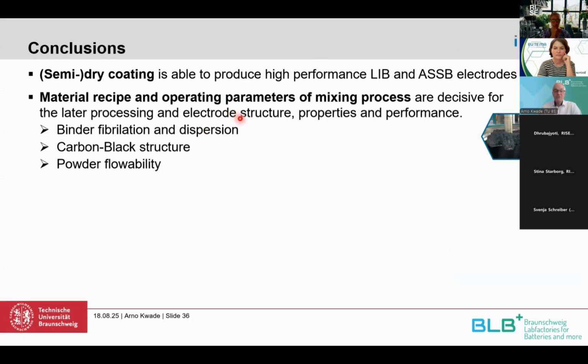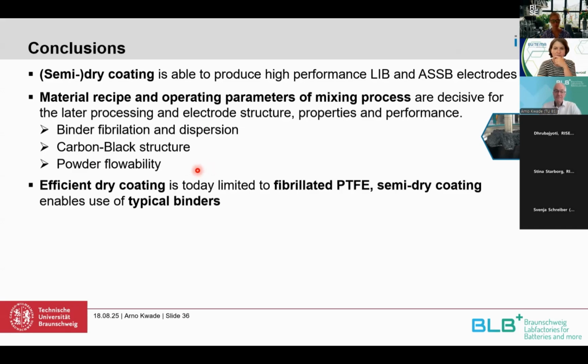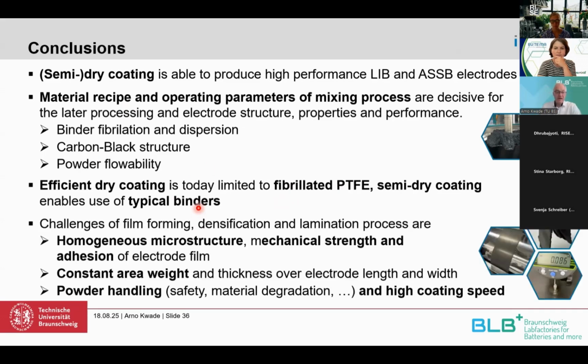That is really crucial for the binder fibrillation, for the dispersion of the carbon black, but also later on for the powder flowability, granular size, and so on, which are then important for the film formation during the calendering process. Today, dry coating is limited to the fibrillated PTFE, so we might find other binders. In semi-dry coating, we can also use typical binders like CMC or SBR.